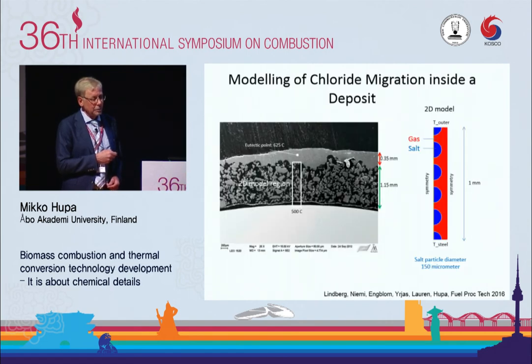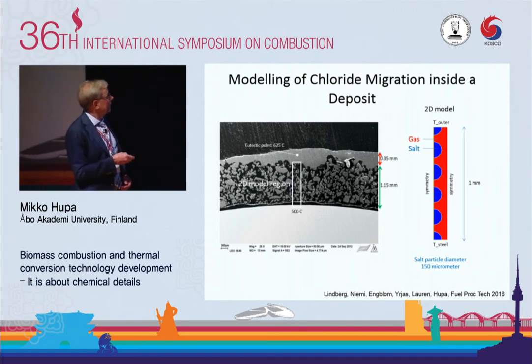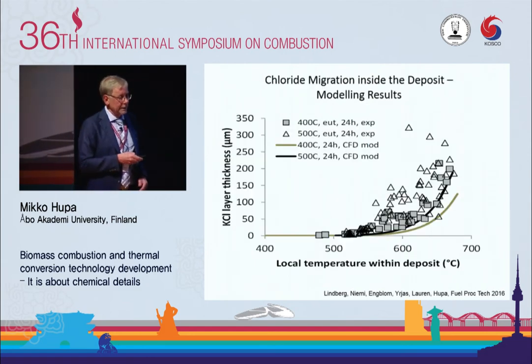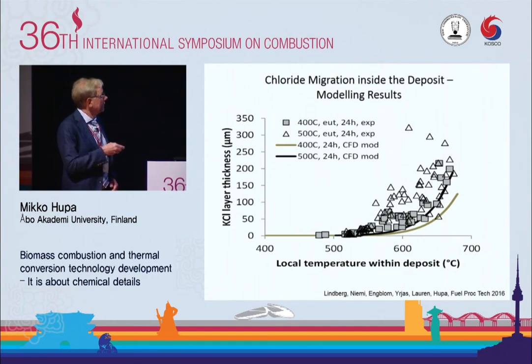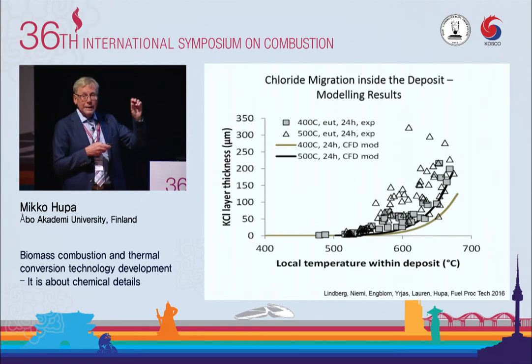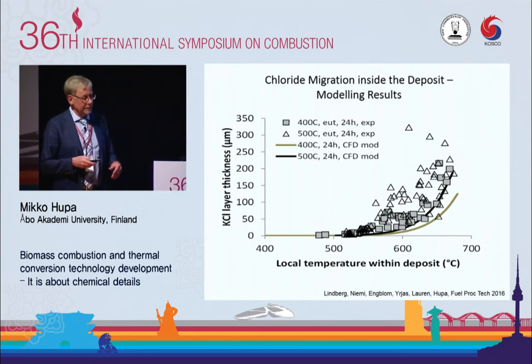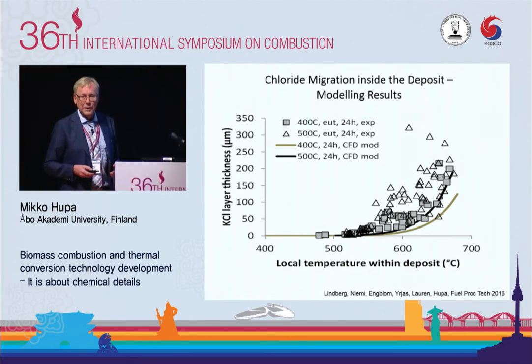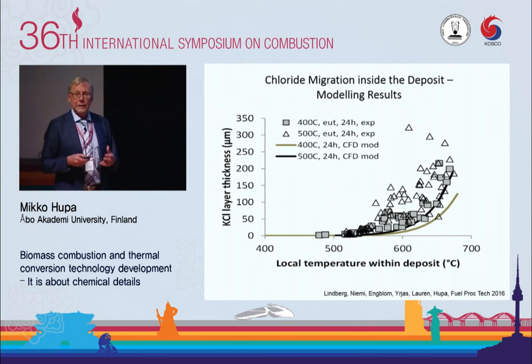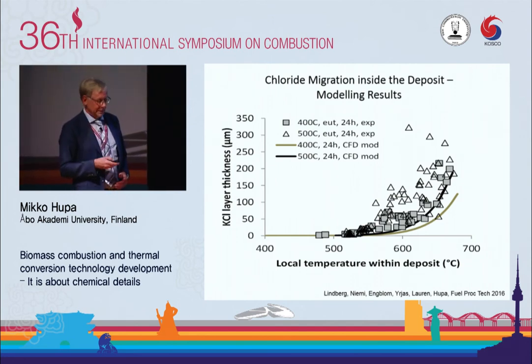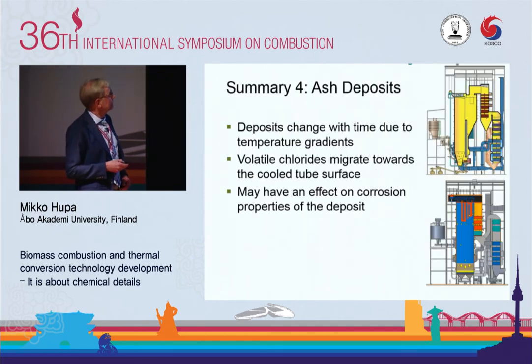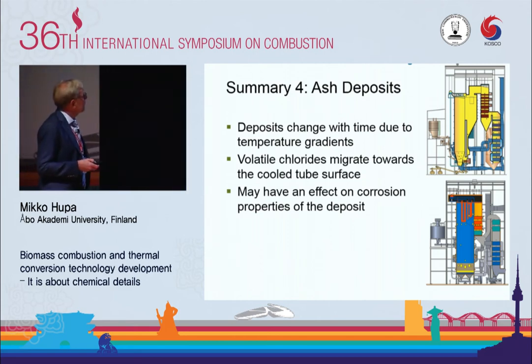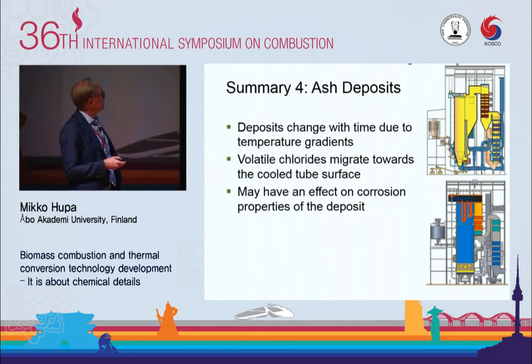We have been able to model this phenomenon by a two-dimensional vaporization condensation model, and we can get some theoretical curves which fit quite well to the layer thickness. We can measure the potassium layer thickness as a function of time. This is a new area. We call it gradient chemistry, inorganic chemistry in temperature gradients. It can be important in other applications as well. Deposits change with time due to temperature gradients. Volatile chlorides migrate towards the cooled tube surfaces, and it may have an effect on corrosion properties of the deposit.